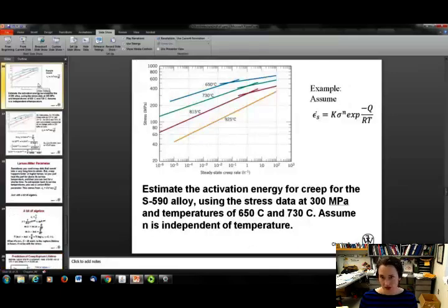Okay, so here, next question. Estimate the activation energy for creep for the S590 alloy using the stress data at 300 megapascals and temperatures of 650 C and 730 C. Assume N is independent of temperature. Okay? So in my example here, I've got my equation for my creep rate. Epsilon dot is equal to K sigma to the N e to the minus Q over RT. So that's my assumption there.